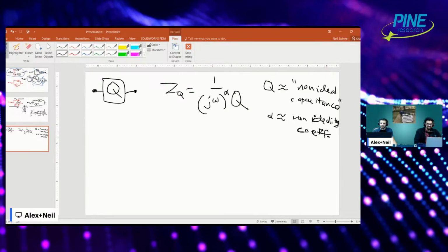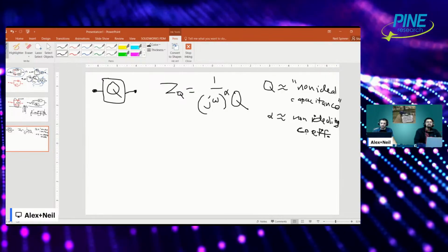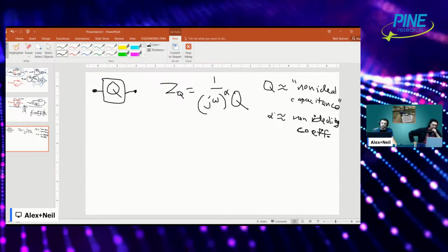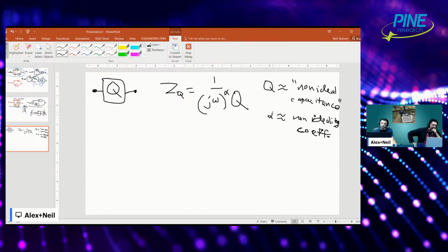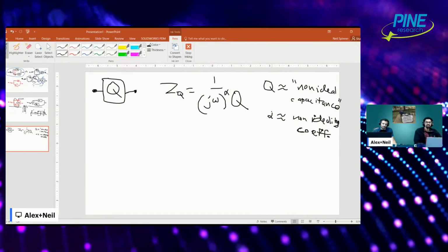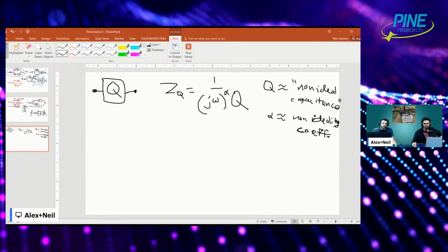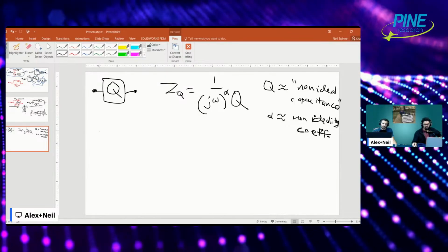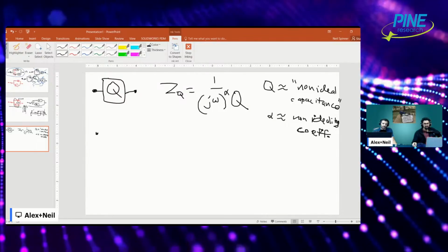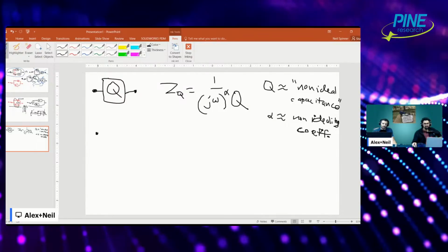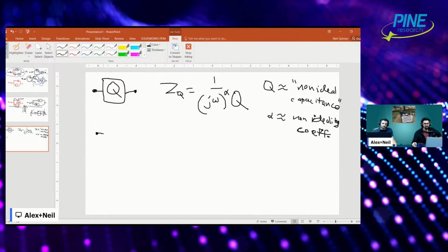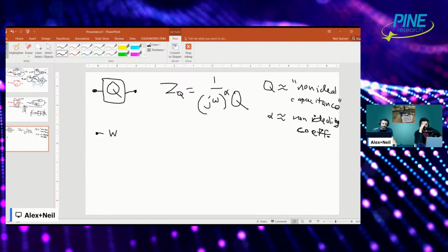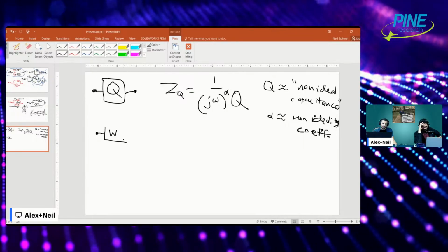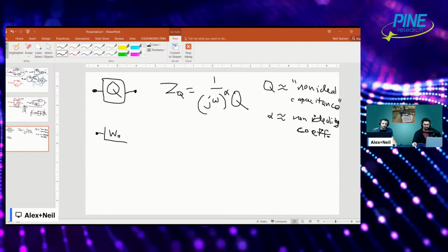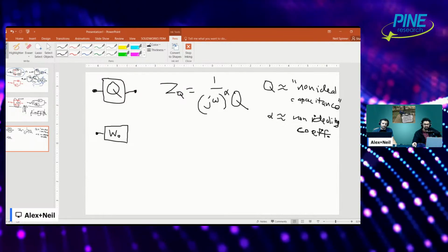That's right, exactly. But alpha is usually between 0 and 1, and it's a degree to which your capacitive element, so to speak, is ideal or non-ideal. So if you're talking about including both of them, usually you do, in a paper or a presentation. You'd say, well, my Q is this value, and alpha was 0.9895, indicating close to ideal behavior, or 0.7, so it's very non-ideal or whatever.